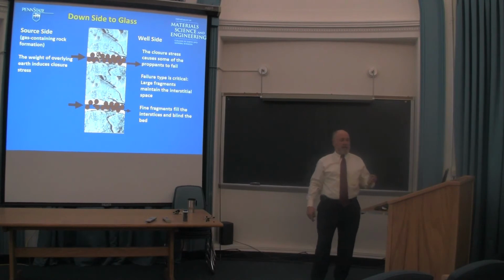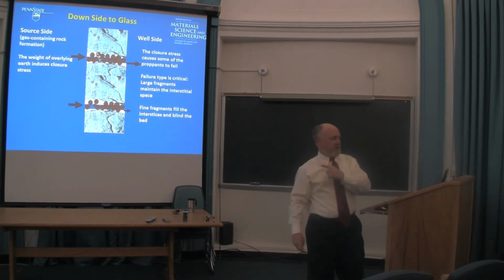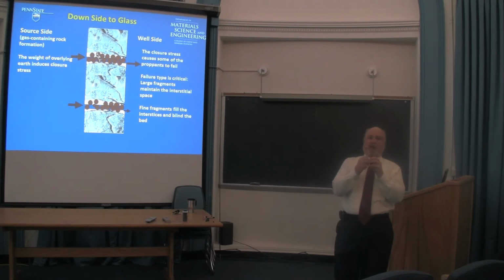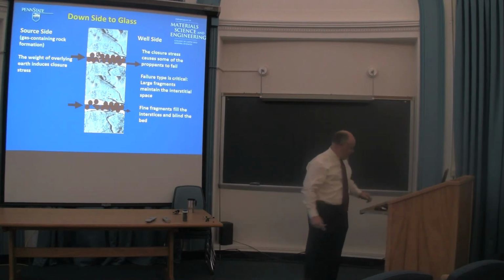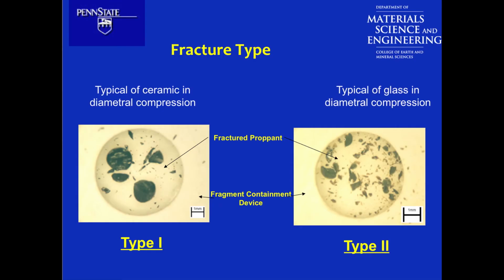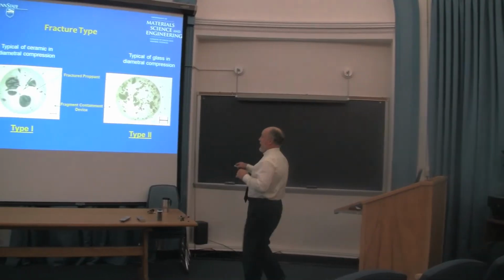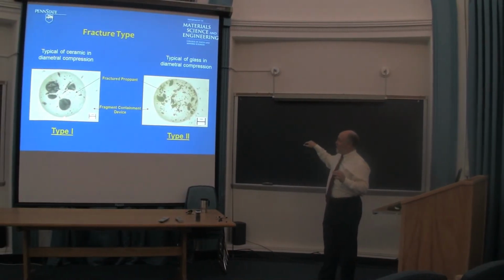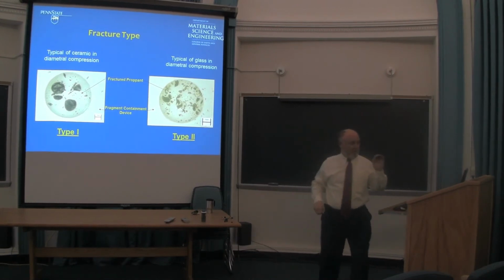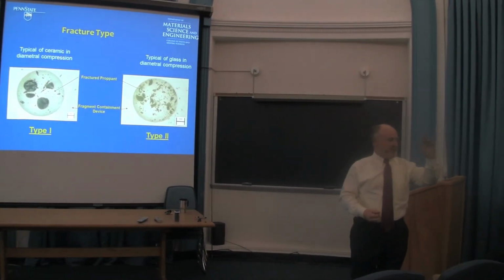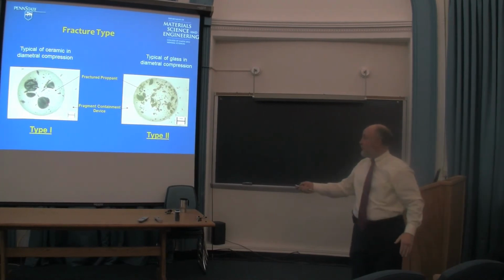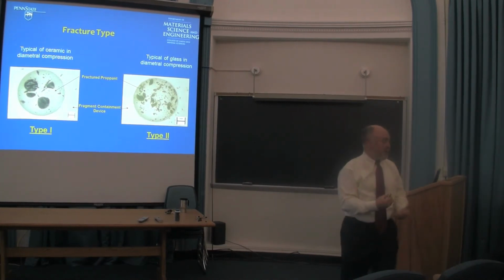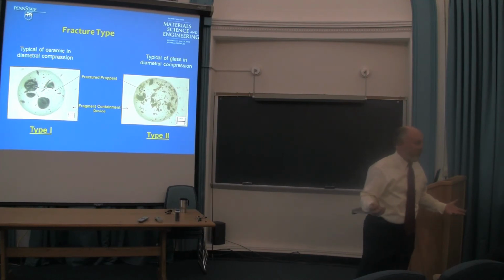So we have to find a way to alter that fracture behavior such that it doesn't fail into fine particles but fails into bigger chunks. All right? Well, one way you can do it comes out of other work that we did at Penn State over the years on tailored residual stress profiles in glass. All right? What you're looking at here is this circle is a hole in a piece of paper that we put one proppant particle into and then squeezed it to failure. So these are the fragments remaining from that proppant particle blowing up when we broke it.